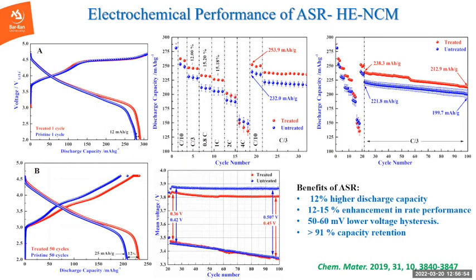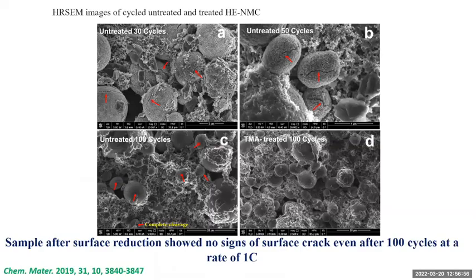And the way we are capable of following the surface of the cathode, can you see here the crack and the crack? So the uncoated one, if the gas is evolved, the battery is cracked over time. But when the evolution of gas is suppressed, we do not see cracks. And again, if we take SEM and follow every particle, we did not count thousands of particles, but we couldn't find significant cracking.